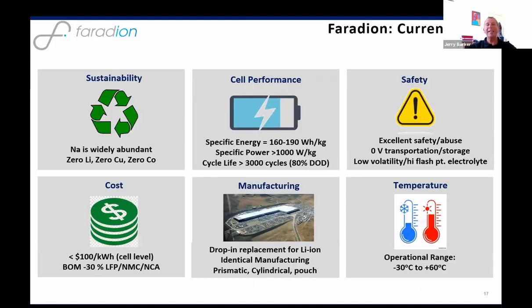And thus our current status at Faradion, just to give you a summary. So we think we're very sustainable. Sodium is widely abundant and we're zero lithium, copper, and cobalt. Our cell performance is specific energy 160 to 190 watt hours per kilogram. Didn't mention specific power, but it's over 1,000 watts per kilogram for our energy product, which is very good.